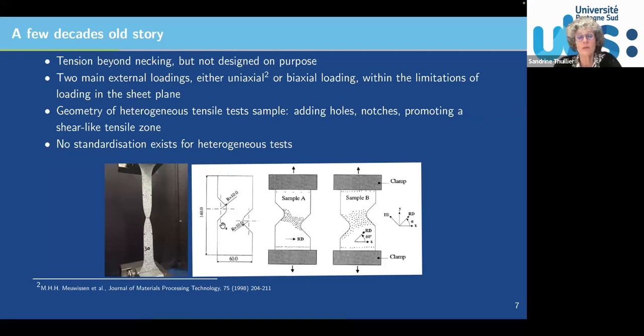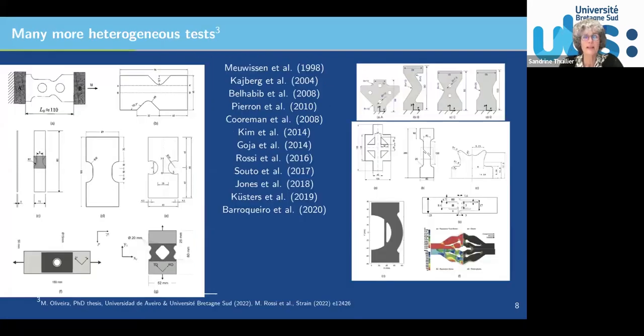So the idea was to use discontinuity in order to control where the heterogeneities will occur in a sample. And so the idea is to add holes, notches, to promote shear-like tensile zones. The main issue, I would say, is that there is no standardization for these heterogeneous tests, which means that there is a large number of them. And here is maybe the first one, 1998, but you can see it has been a kind of ongoing activity, and we still have new tests coming.